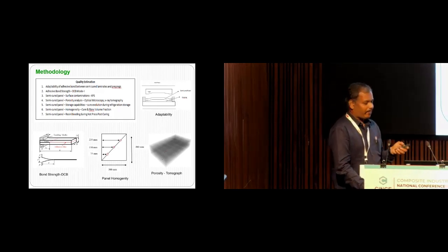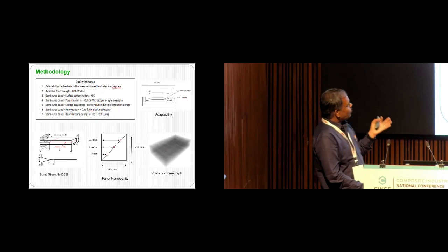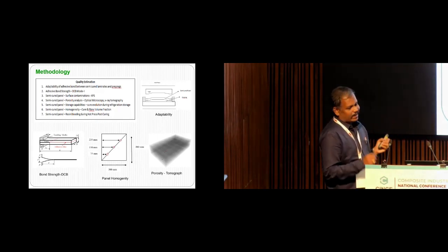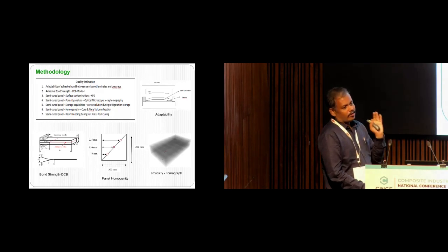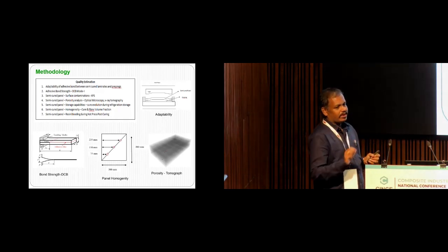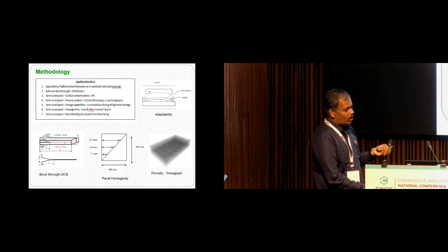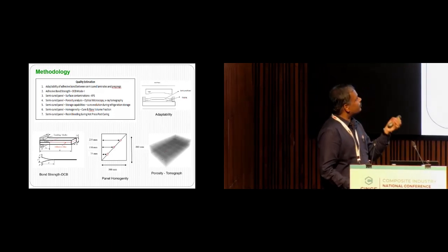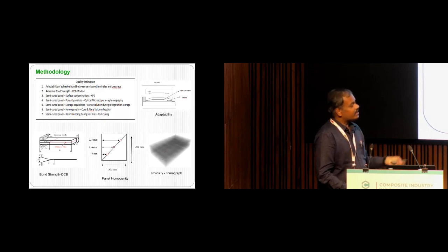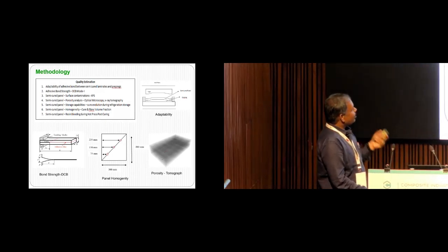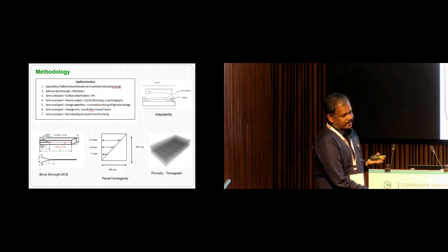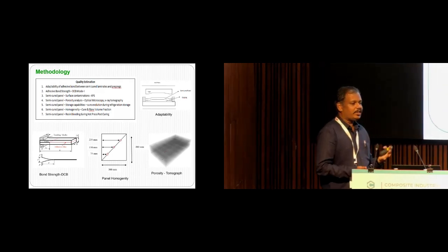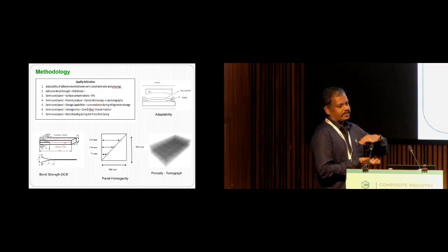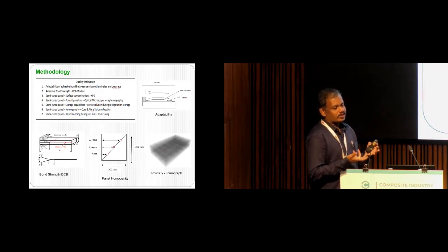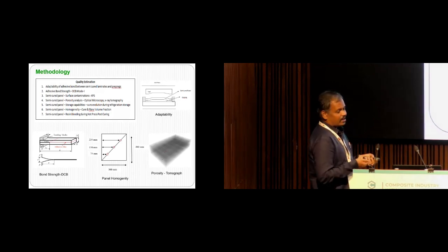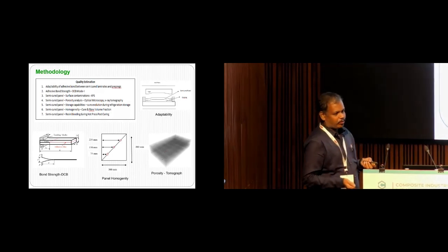And I should find out the panel homogeneity through degree of cure measurement as well as fiber volume fraction. With respect to different dimensions, you have to find out the degree of cure as well as volume fraction. That should be uniform across the distribution. Next, you have to analyze the resin bleeding. When you transport, obviously you may transport the layers under a certain pressure. So you should know how much resin bleeds out when the laminate consistency is semi-cured.